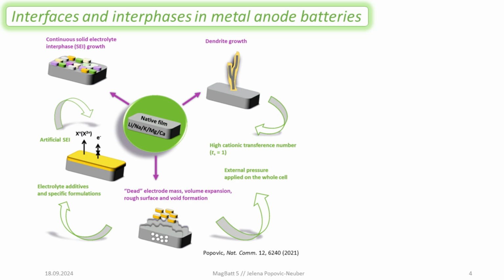From the previous talk, we have heard that in the magnesium case, that seems not to be the biggest problem. But in any case, we do have some kind of non-flat electrodeposition. So some people deal with anodeless morphologies and cells where we are trying to avoid non-flat deposition by having already porous current collectors.